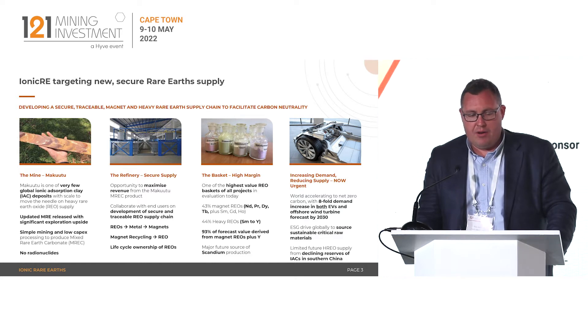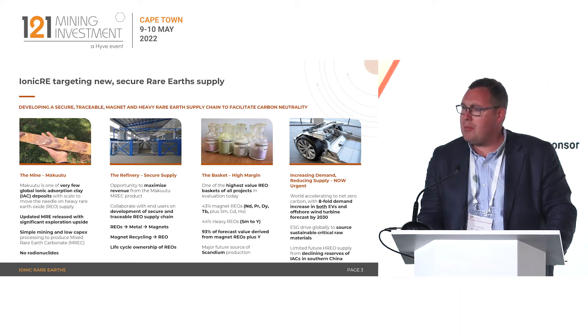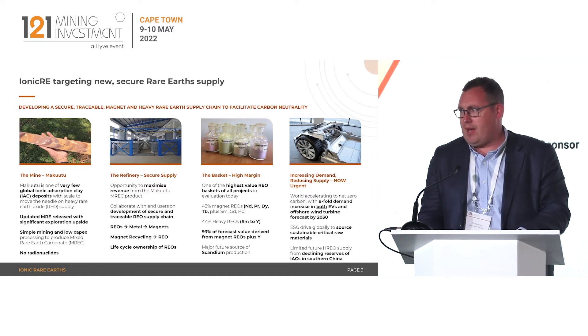We are working on a feasibility study at the moment. That feasibility study will consider a very simple modular development — heap leach — where we effectively wash the clay with salt solutions, which extracts the rare earths in a chemical form that we can precipitate as a mixed rare earth carbonate with no radionuclides. That product would be exported to a refinery. We're completing a location analysis, looking at a number of jurisdictions, with the ability to separate the mixed rare earth carbonate into individual rare earth oxides that can then be used to make value-added metals, alloys, and ultimately magnets.